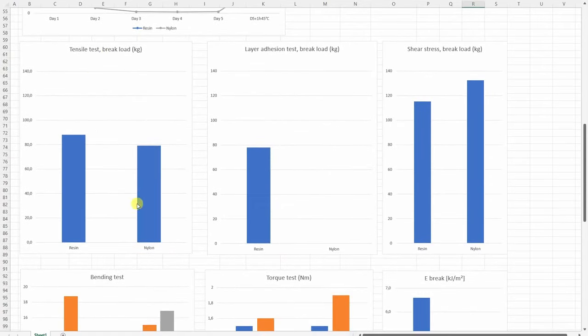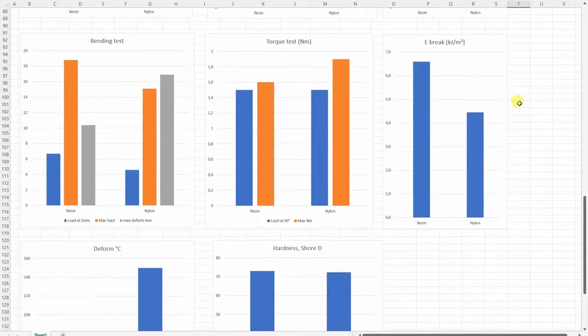Tensile test, well, the resin is a little bit stronger compared to the nylon, but this is interesting. So the layer adhesion test, here the resin printed in vertical position is almost as strong as the horizontally printed version. So this is what I like with this kind of materials. The shear stress, well, the nylon was a little bit stronger here.